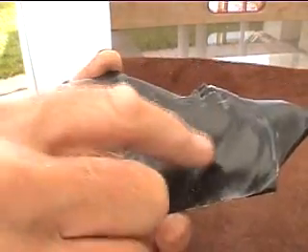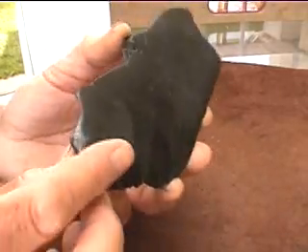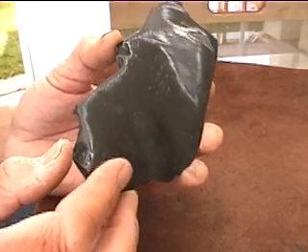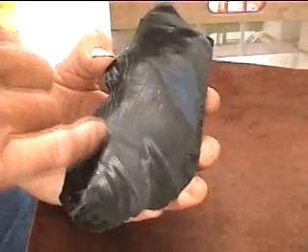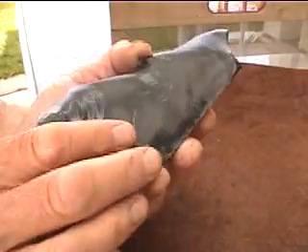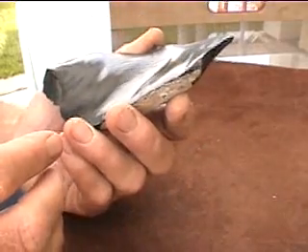These little fractures in a flake actually weaken it. This can be made into a small biface or an arrowhead or a dart point, but when you're working with a flake, bear in mind that it has already been bent when it was detached from the core. As a result, it's not as strong as rock you would just start working naturally — it's not as strong as the core itself. Cores will make stronger points and will be less likely to fracture during manufacture. I've had a lot more flakes like this break on me when pressure flaking or bifacing them out than I have with cores.